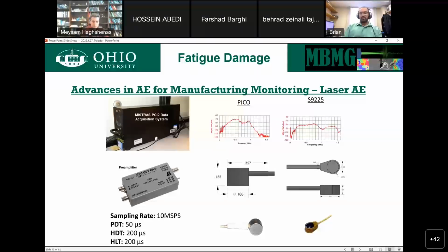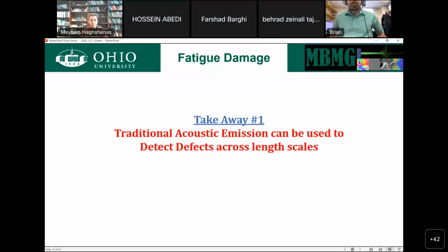And for that reason, we've explored replacing these with a laser vibrometer so that we can do this without actually making direct, physical contact with the material, and it allows us to get acoustic information on test regimes that otherwise is not a practical solution. So the first takeaway from the talk I'm giving today is that traditional acoustic emission can be used to detect defects, and it is scale independent.